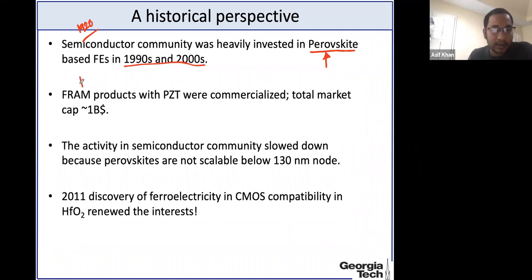And actually, there is a product that came out of all the work that was done in the 1990s and 2000s. This was using a material called lead zirconate titanate, in very low power memory devices that are used in smart cards. And the total market cap of this product is around $1 billion. But eventually, starting with 2000, the activity on ferroelectrics died down because perovskite materials are not compatible with mainstream semiconductor manufacturing, and cannot be scaled down below 130 nanometers. So by 2010, there was almost no activity on ferroelectrics in the semiconductor community. The material science and physics community has been pushing the limits of ferroelectric materials, but in the microelectronics community, the activity almost died down by 2010.